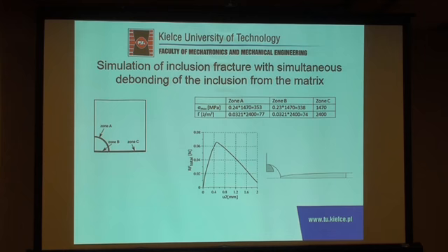well, this is another example. Decreasing of stresses below 23% of cohesive stress for zone C leads to a change in behavior of this cell, because the first stage of damage was again debonding of inclusion from matrix. I tried to, let's say, get the situation again in which inclusion breaks and the debonding takes place also.